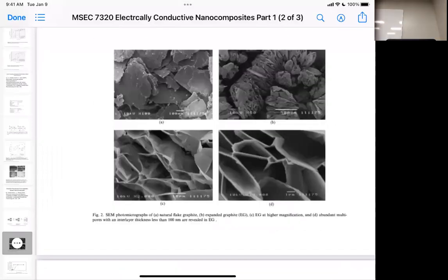So when we look at the grainy part of the particles here, we can see the edges of the particles on the regular stuff. This is what they look like here. So this is hundreds of plates of graphene in each one of these little platelets. That's full graphite. Okay, and then when you intercalate them, it expands a little bit right here. But once you take that and expose it to rapid heating, you get these structures here. It can't completely blow apart. It's not volatile enough, but there's enough energy between the plates to keep some of the little pieces together. But there's no force making them go back together. So they stay expanded. So this is what we can call expanded graphite. So it still has some of the features of graphene, but it's not individual plates we have to worry about. Each of these might not even be individual graphene sheets. They might be 2 or 3, but it's definitely much higher surface area than the unexpanded graphite.